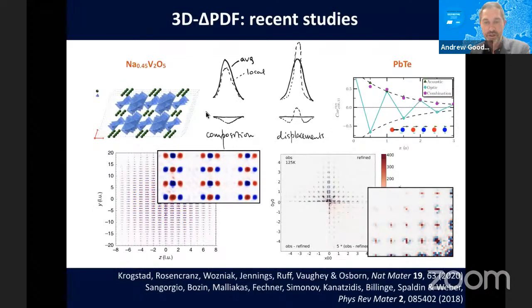Here are two nice results from other groups using these approaches, just to show you what these look like. It's a recent result really coming out of Ray Osborn and his collaborators. This is a sodium intercalation compound, vanadium and oxygen. And these spots that you see here, plus or minus and so on, are telling us that certain pairs between these sodium sites are either occupied more frequently or less frequently than you would expect from the average structure. And this tells us about the arrangement of the sodium ions in the intercalate.